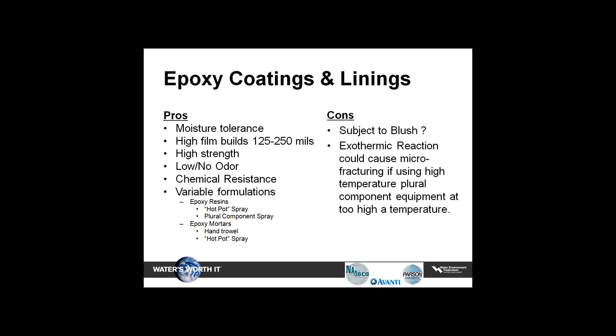The cons of these linings, well, they're subject to blush. There's certain constituents in this product that create a waxy film on the surface. That doesn't really matter, it's in a manhole. The exothermic reaction, though, if the materials are applied too hot, is going to cause a cracking or a brittleness of the film.